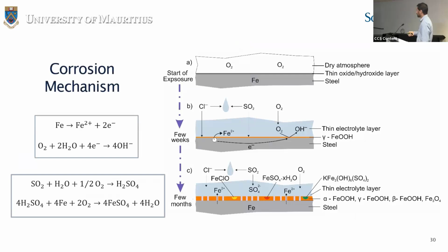This figure is a schematic time profile of the corrosion products evolution under the regional effects. The uncontaminated surface has a passive, thin oxide hydroxide layer. And after a few weeks, you could see the brownish lepidocrocite layer, which forms as a thin electrolyte film comprising chloride and sulfur dioxide sets on the surface. The next stage of rust development shows the transformation of lepidocrocite into the stable goethite rust phase, and also there are formations of other rust compounds like iron oxychloride, iron sulfate, and jarosite. The rust layer also grows as a porous membrane, as seen here.